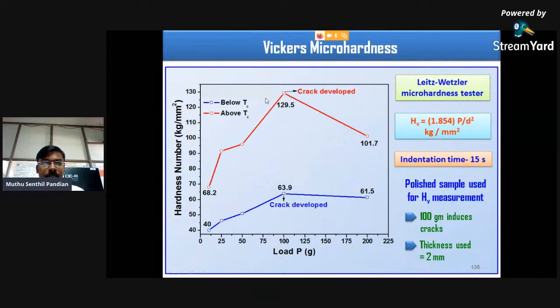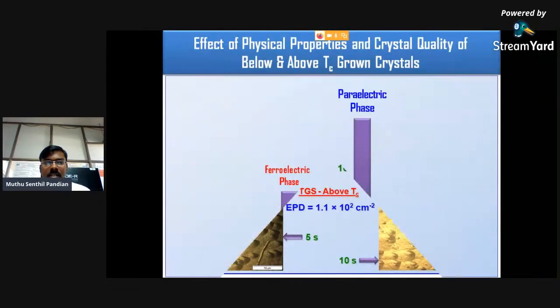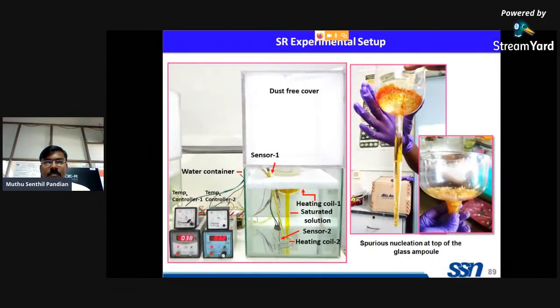And this is the Vickers microhardness measurement at the paraelectric phases. The physical properties and the crystalline perfection of the crystal grown in the paraelectric phase are highly comparable to the ferroelectric phase grown TGS single crystals. So this is a modified exploded setup of this SR method. We have grown 2-amino-5-nitropyridine derivative single crystals by this SR method.